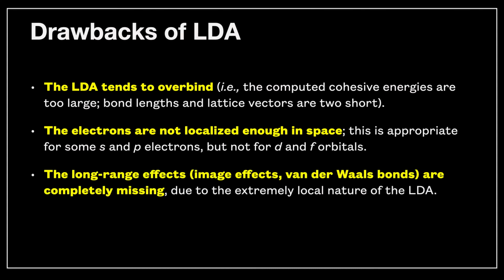LDA does not have any long-range effect, and again, not surprisingly, since it's a purely local one, so it only considers the local properties of the problem. So everything that has to do with image effects, for example the interaction between adsorbates and a metallic substrate, or van der Waals bonds, which are purely non-local, dipole-dipole interactions, and I'm going to discuss that in a few minutes. These are completely missing. And I'd like to insist that they are missing completely, not just wrongly described.